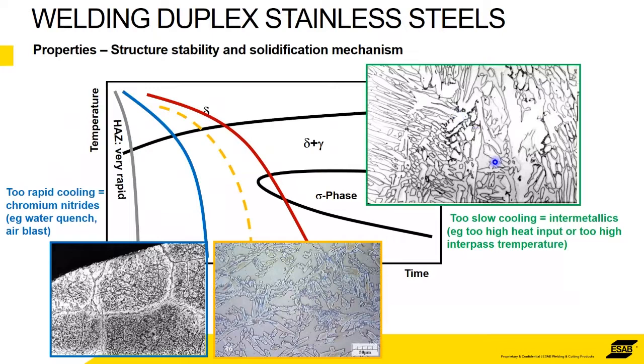Okay. How do you get too slow cooling? It means it's got too hot: too high heat input, or too high interpass. The welder couldn't wait for the interpass to go down below the recommendations, below the 150 or the 100. He wanted to get another pass in before he went home. There's too much heat in there, so it's cooling down too slowly. You're going to be within these areas where you're going to generate the intermetallics.